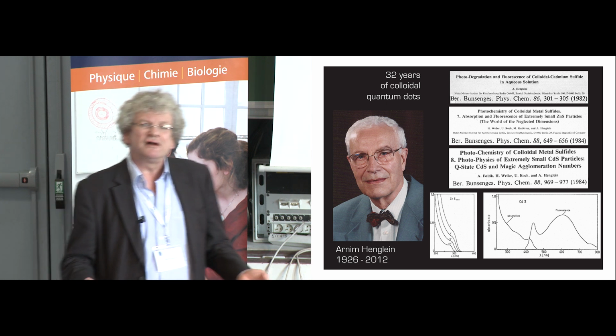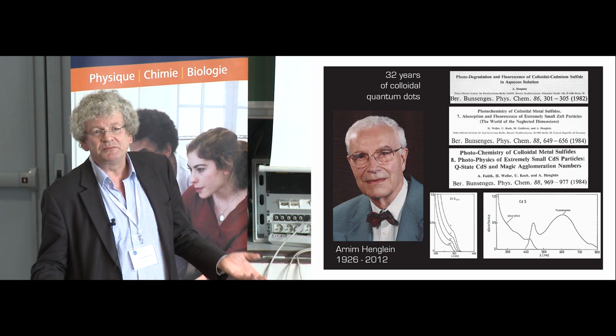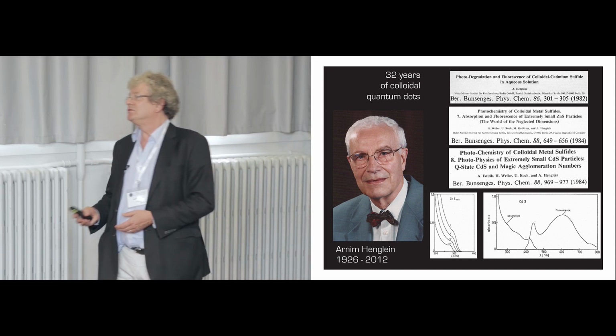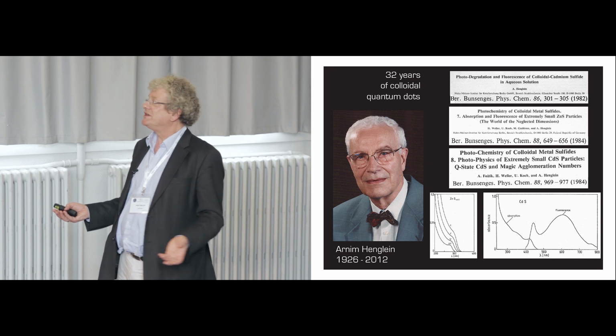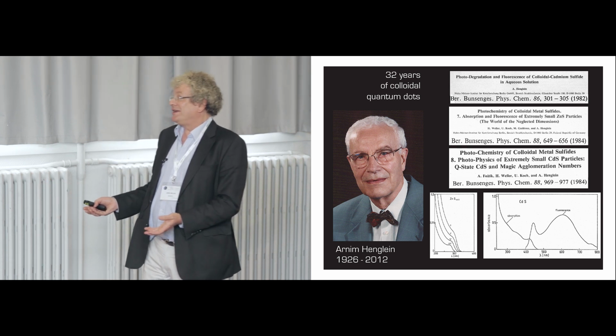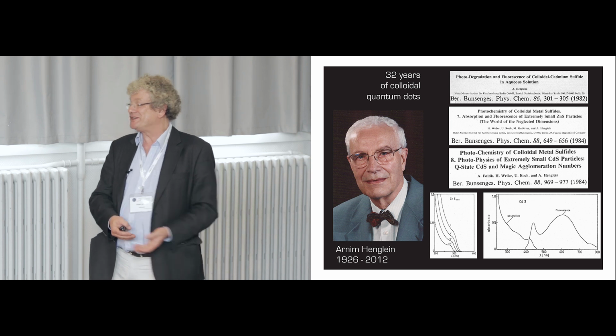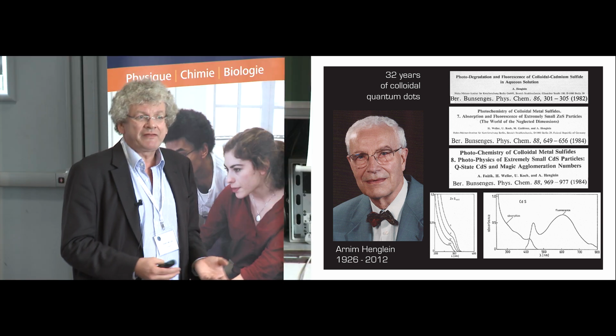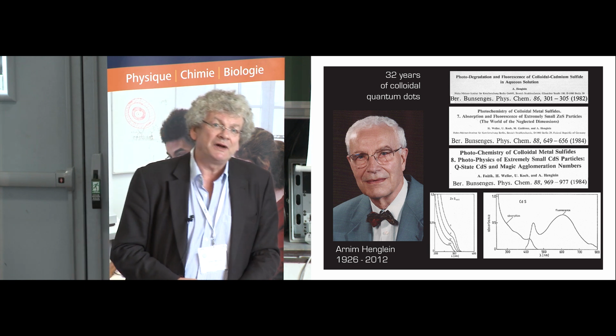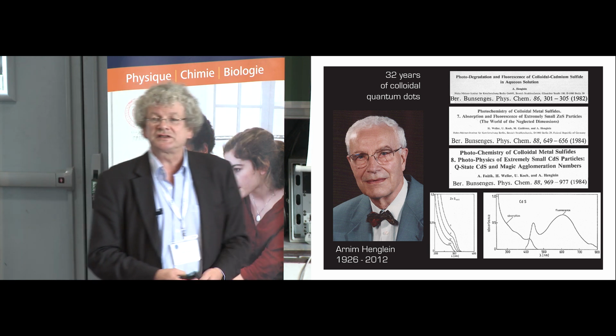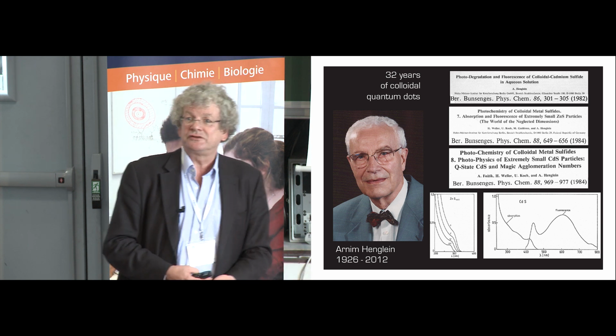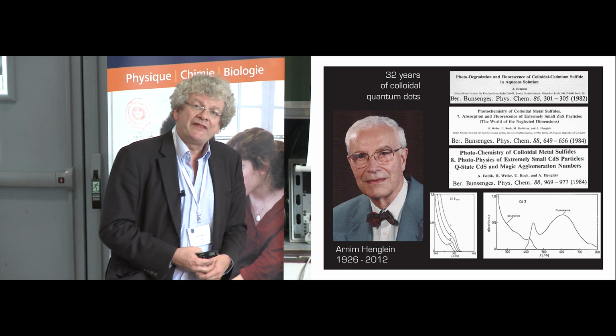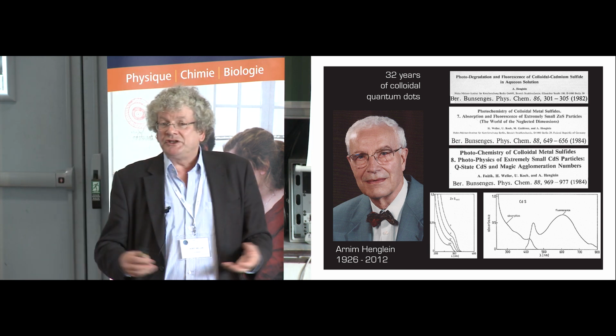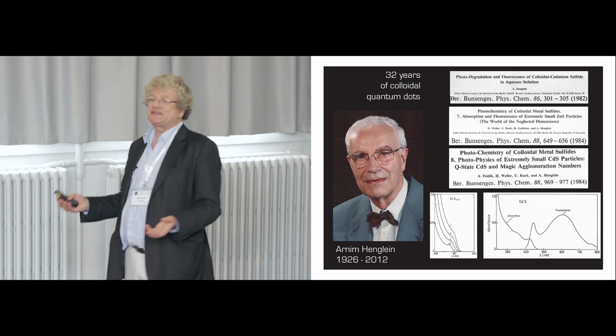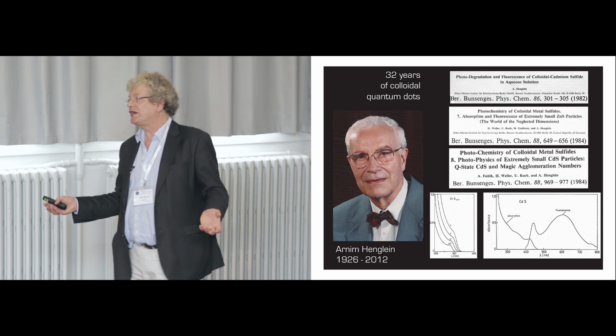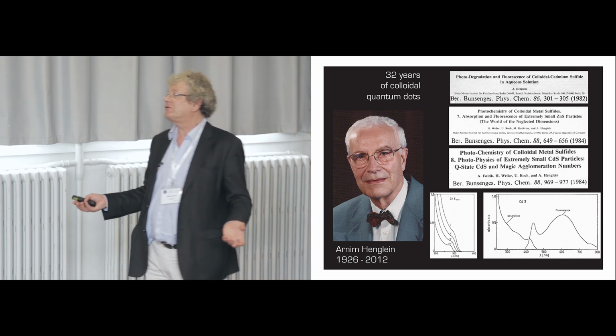And people were thinking of how to make artificial hydrogen. And that was the beginning of how this field merged together with people from photoelectrochemistry, who of course did not use gamma irradiation. We don't want to have gamma irradiation to make hydrogen, but used solar light. And that was the beginning somehow at this point where people tried to use small semiconductor particles to make artificial photosynthesis. Many people used suspensions, and the idea was, let's make them smaller. Smaller because then the charge carriers are immediately at the surface and they can do the catalytic reaction.